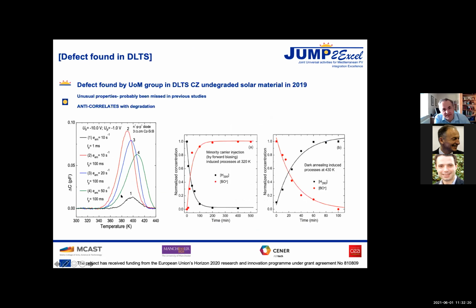Okay, so this was our contribution to this in 2019. We found a defect in DLTS, and it turns out that you need quite a high temperature to ionize it, and that's not so much because it's a high binding energy, but because there's what's called a high activation energy. And so we found it, but it's curious because it's a donor, and it's a deep donor, and we don't understand how that causes the behavior. It shouldn't be. It should be a minority trap. It doesn't have the right characteristics, so that's a low cross section for it.